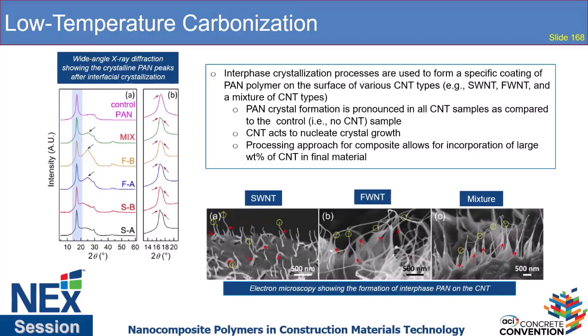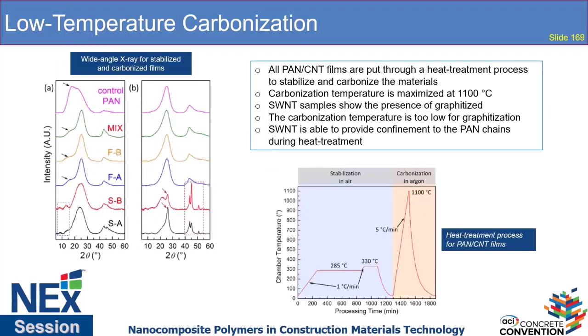And so here this just exemplifies that we can do it, and we can do it for a lot of different systems. But then when we try to carbonize it, and in this particular case we're carbonizing it only up to 1100 degrees C, which is not at industry standard, but it is something where we're forming a carbonaceous structure. What we found is that you can form an amorphous carbon, but when you use single wall nanotubes, you can form a graphitic structure.